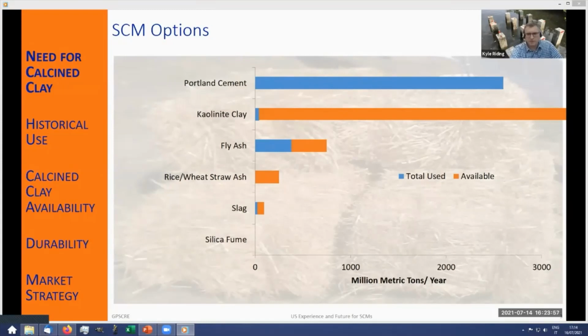that decreases the sustainability of the material. Also, you have impurities in the materials, like for instance, you have phosphorus in corn stover that would need to be removed in order to not damage your concrete. And that takes either a dilute acid treatment or water soaking, something like that to leach it out. And that's expensive and reduces the viability of the material. So there's a lot of issues with some of these materials. I don't want to get too much into it because that's not my main focus. But you can see that of the other alternatives, really clay is the one that has the available material that we can use worldwide to